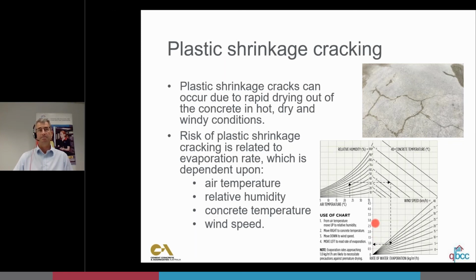You might need to do things like put up windbreaks, try and do the walls first if it's a commercial building, or use aliphatic alcohol. Aliphatic alcohol, or anti-vap, is a substance that you spray on as a fine mist once you've screeded and bull floated the concrete, and it helps prevent evaporation of that bleed water. So you don't need to use it all the time. You just need to use it when there's a risk of high evaporation and the surface drying out. If you do use it, you need to use it as a fine mist, and you need to reapply it every time you undertake a finishing operation on that concrete.